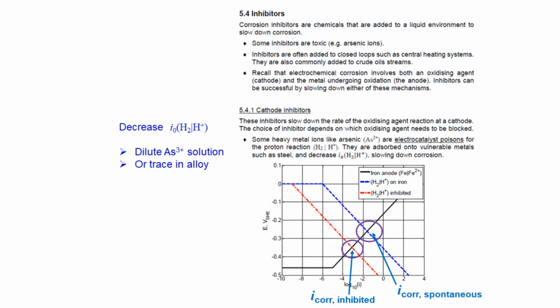If I can do something to my metal to change the exchange current density for the hydrogen reaction and make it smaller, in other words, if I can somehow add an electrocatalyst poison, then I can find this situation of the second intersection, where I have the intersection of the iron dissolution anode with the red line, the inhibited cathode. By decreasing the exchange current density for the hydrogen reaction, I have slowed down overall corrosion rate, I've inhibited corrosion.